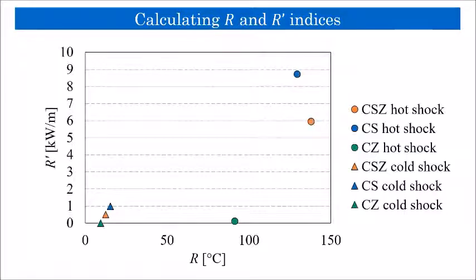After most of the material properties are measured experimentally, thermal shock indices are calculated. In this graph, the calculated value for mild shock index R prime is plotted versus hard shock index R for all three compositions.